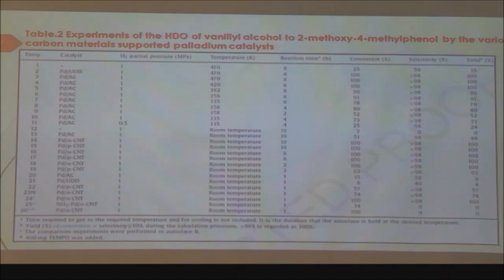Here we see that the catalyst was able to convert this vanillyl alcohol to 2-methoxy-4-methylphenol. So here only one methyl group was generated and the phenolic group was not released. What we concluded is that this catalyst was somehow converting the CH2OH group into an alkyl group, but not the phenolic group into benzene. That was the one thing we came to know from this study.